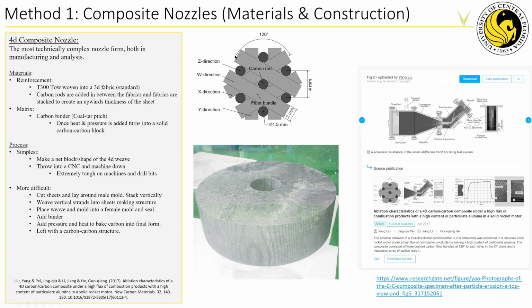Essentially they have sheets of this carbon fiber with tow directions in the X and Y directions, and then you have a Z direction with carbon rods fit in vertically, so you build up a structure. For what they described in this research article, it's T300 tow woven into a 3D fabric, and then the carbon rods are added in between the fabrics every 4 millimeters, shown up here. Each rod is 1.5, and each tow is about 2 millimeters.